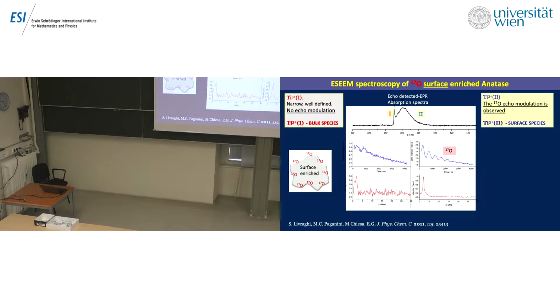The second species must be at the surface because of this modulation, and so the model we derive is that there are few titanium sites in the middle, far away from the surface, and a high number of sites at the surface close to the vacancy, and this also explains the heterogeneity of the system.